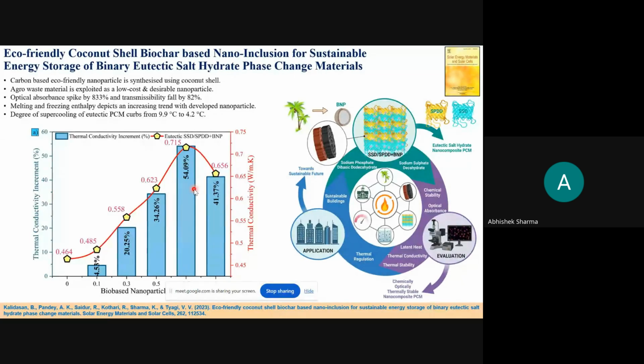And then we did this study because we were looking into more sustainable options. Some nanomaterials are readily available, but sometimes the synthesis process is energy intensive, when we go for 3D, 2D, and all, in nano scales. So what we have done, we started looking into waste and converting the waste into nanoparticles, or not exactly nanoparticles, we stopped at micro scale. The size was roughly around 400 to 500 nanometers, so you can say microparticles.